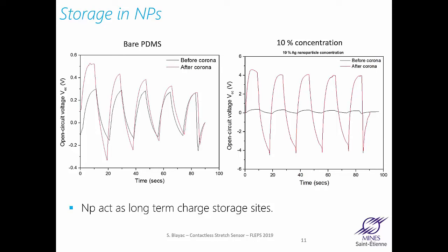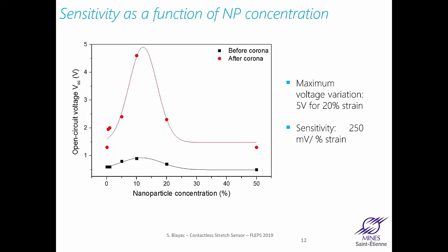So the nanoparticles act as long-term charge storage sites, and we are now able to have a contactless sensor. So we studied the signal and the sensitivity as a function of nanoparticle concentration, and we obtained a maximum at 10% concentration with a good sensitivity of 250 millivolts per percent strain, which is rather interesting. And the second thing important to see is that even without corona, we have some variation, and it's probably due to implicit triboelectric effects in the film that we designed.